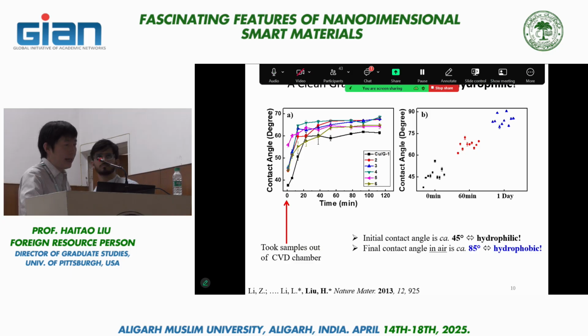Okay. So what you see is about 6 different samples. And for every sample, we do about 10 different measurements at 10 different locations. And so we record the contact angle as a function of time. Again, time zero is the time when we take the sample out of the CVD chamber. So what you see here is a very obvious time dependence. The initial contact angle we measure is around 40 degrees. There's a large scattering. But despite this large scattering, you see this rapid increase of water contact angle, and it plateaus around 65 degrees within